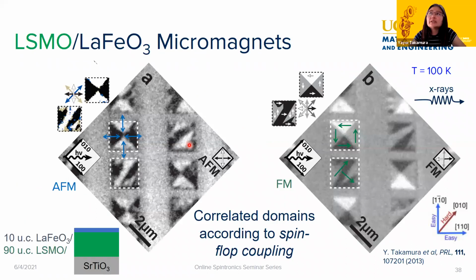Yeah, so we haven't done it in the PEEM just because it's an electron microscope and you can't actually image with a field on. You can apply pulses, right? And then image in remanence. So with those, we definitely see that both the ferromagnetic and antiferromagnetic domains change with the pulses. But we've also done it with spectroscopy for unpatterned films and shown that you apply a magnetic field and the antiferromagnetic spins rotate to be perpendicular to that. So we're pretty confident that's what we can do. Those measurements would vary: we're going to apply a different orientation of the magnetic field and, ideally, rotate the antiferromagnetic spin axis.